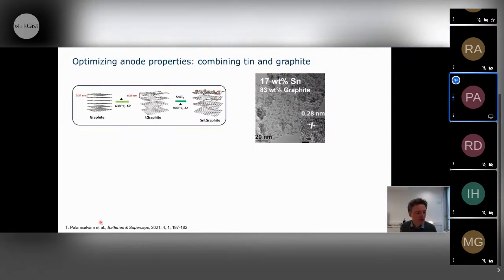This is a study we published recently in Batteries and Supercaps. In order to increase the capacity of graphite, first of all, we were adding tin. So this is a composite containing 17 weight% of tin, and all the rest is graphite. This is simply done by thermal treatment. We take tin chloride as a tin precursor, mix it with graphite, heat everything up, and then you have tin distributed over your graphite matrix, so to say.